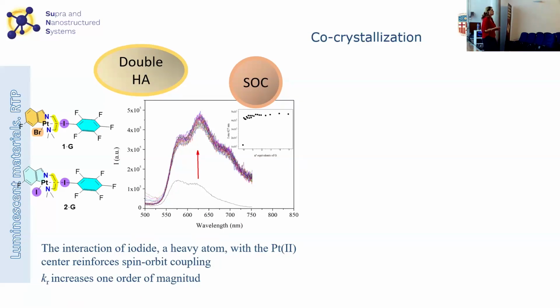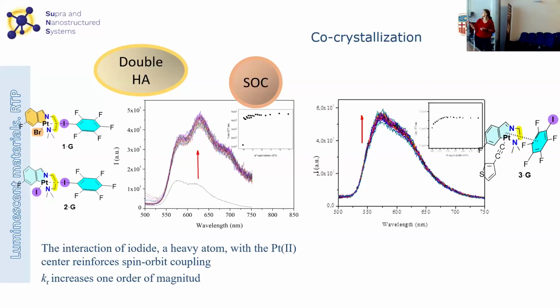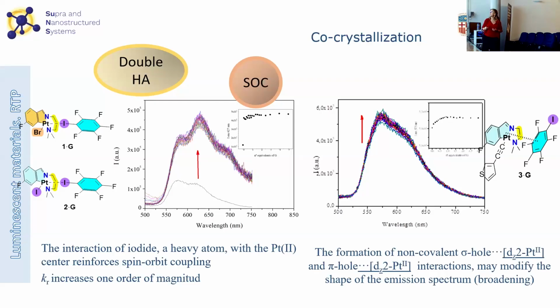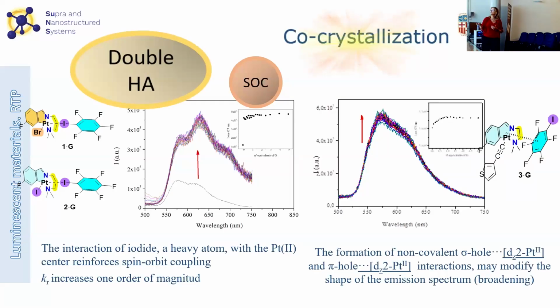And this is what we called the double heavy atom effect, since we have one heavy atom, the platinum in our molecule, and a second heavy atom, the iodine in the guest, that is affecting the resulting luminescent properties. On the contrary, when we have these pi-pi interactions but there is no platinum-iodine bond, the differences in the emission spectra are really small. So this double heavy atom effect cannot be directly ascribed. We require the direct coordination between the platinum center and the iodine. And we think that it should be further explored, since the combination of co-crystallization and the double heavy atom effect can be really interesting for us in self-assembly and luminescence.